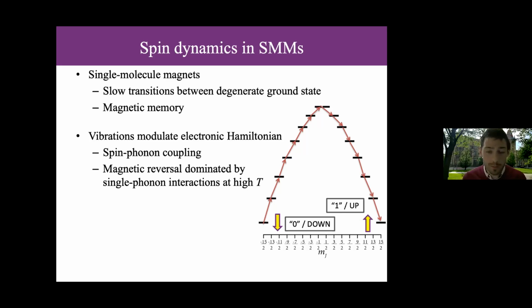any real experiment, we have a solid sample. Even if it's a solution phase, you still have an extended material, right? And so in these cases of solids, we talk about phonons. These are quantized vibrations in the solid state. Crystalline or amorphous phase, because you still have phonons in amorphous phase as well, which is something we're starting to think about. Whereas in chemistry, we're usually talking about vibrational modes in the gas phase, so isolated molecules. And so these terms of spin phonon or vibronic coupling are more or less the same thing, but it does depend on context. Okay, so forgive me if I switch terms, I try to use them synonymously.